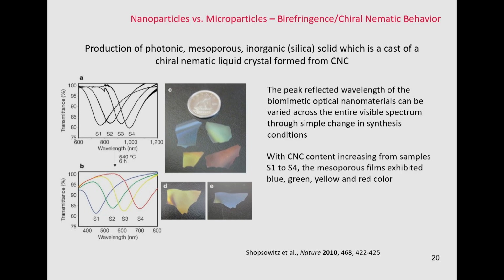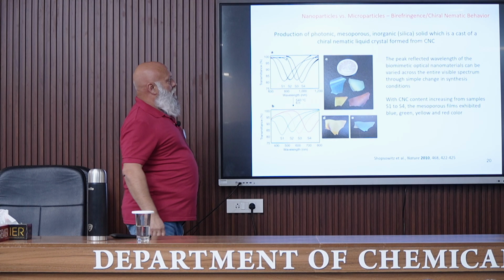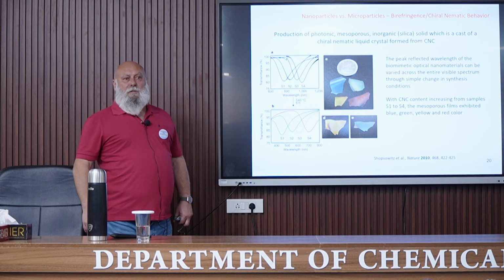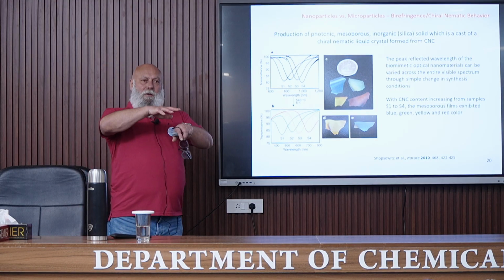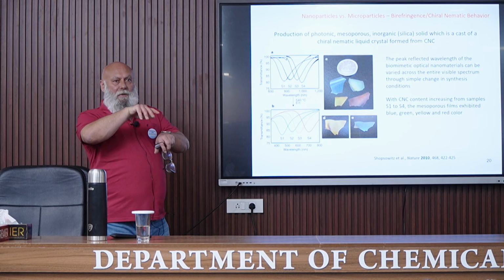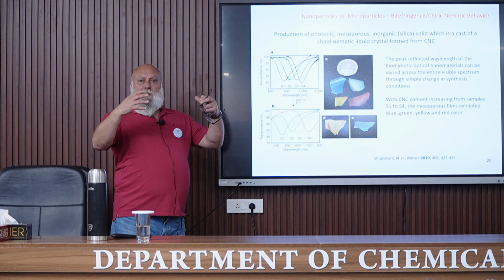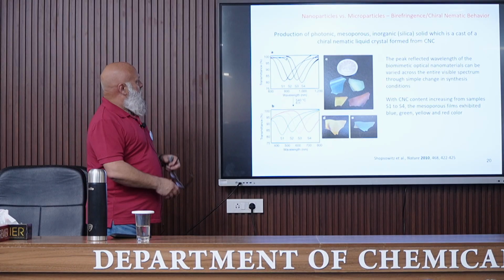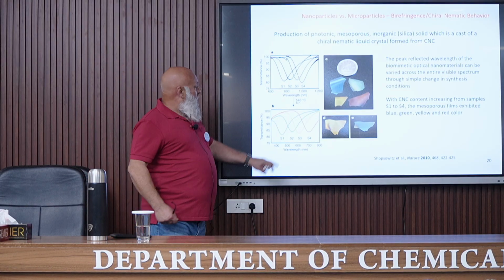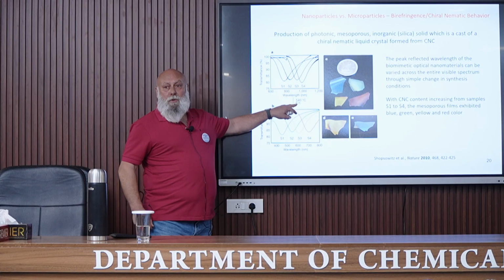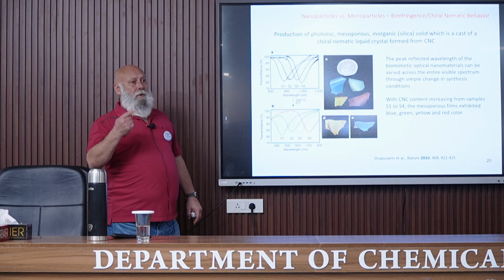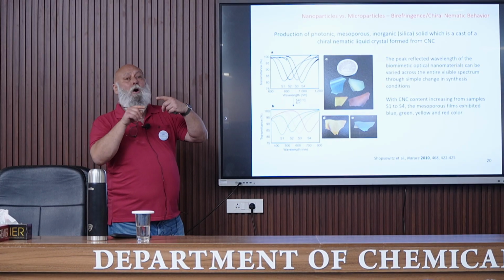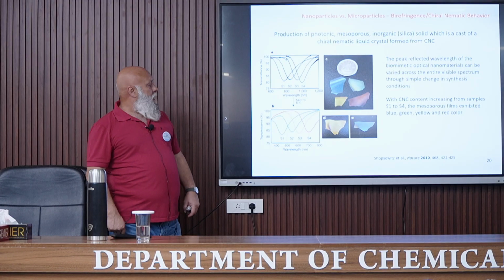Photonic, mesoporous, inorganic silica solids were prepared, and they were a cast of a chiral nematic liquid crystal, which was formed by cellulose nanocrystals. So the cellulose nanocrystals were organized, we have this self-assembly. Silica was formed in the presence of the cellulose nanocrystals, and then by a treatment at high temperature, cellulose was burned, and we keep only the organized porosity of the silica film.